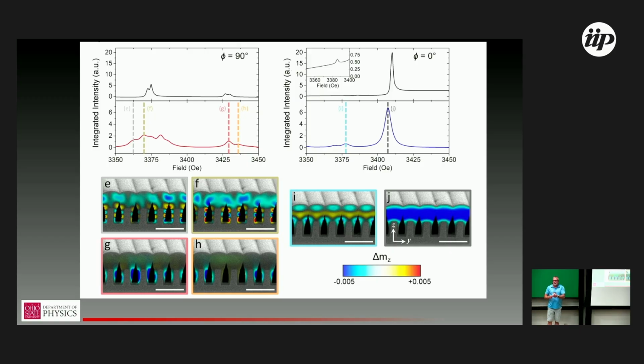So in plane for one of those systems is out of plane for the other system. This is why they have sort of opposite sinusoidal variation. And when we get to the high symmetry directions on the right here, you can see you recover something that looks more or less like a thickness quantized spin wave mode in a thin film, which is what you would kind of expect if you're squinting at this and you miss the fine structure. You've got just a block of magnetic material.